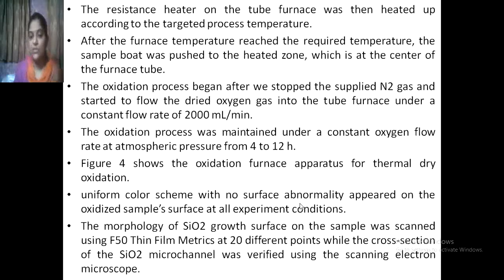The oxidation process was maintained under constant oxygen flow at atmospheric pressure from 4 to 12 hours. A uniform color scheme with no surface abnormality appeared.